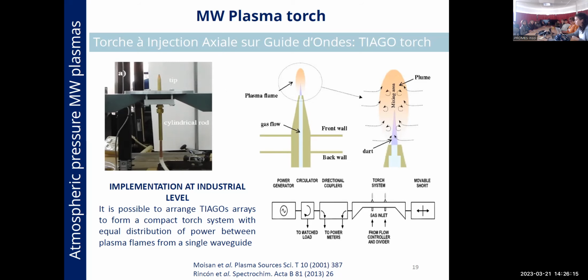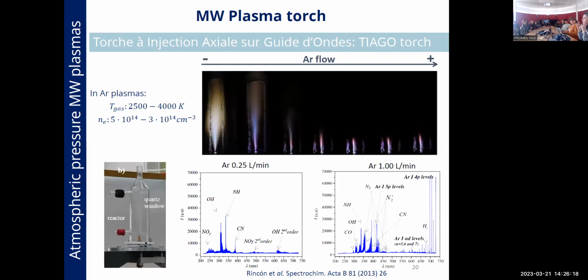As I said before, the discharge is created open to the air at the tip of this field applicator. So we have like this flame, and since it's open to the air, nitrogen and oxygen from air will affect the plasma kinetics. In these pictures, you can see an argon discharge generated with this torch, with different argon flows from a lower value to a higher one. You can see that the morphology and the color completely change.